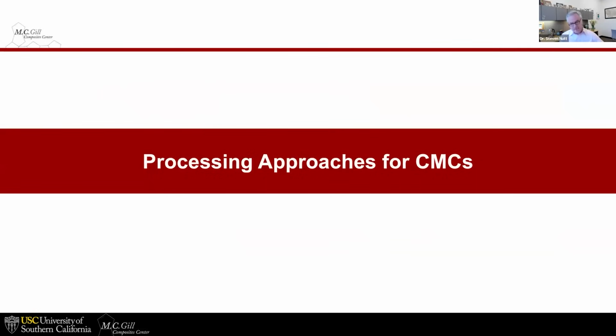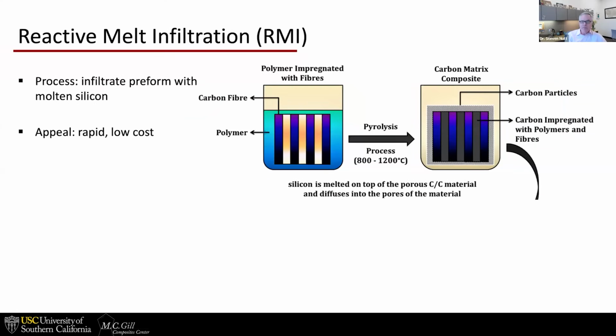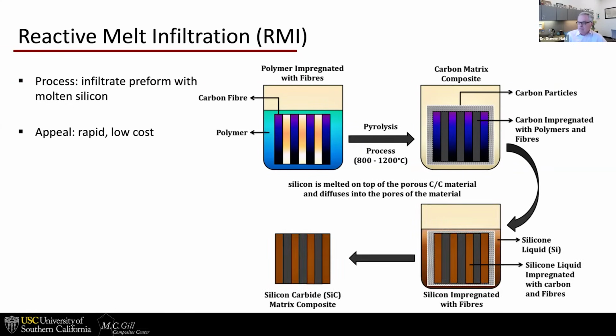All right, how do we make these ceramic composite materials? There's about 5 different answers. The first one that's been around for quite a while is known by 2 acronyms. One is RMI for reactive melt infiltration. It's also known as LSI for liquid silicon infiltration. And you can see in this graphic that basically, starting with a carbon fiber polymer composite, and then pyrolyzing that to create a sort of porous material, and then infiltrating with molten silicon, not silicone, as that annotation mistakenly says there, to flow via capillary flow into the porous preform and react to form silicon carbide.